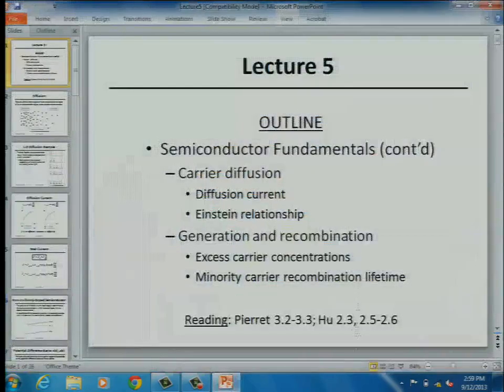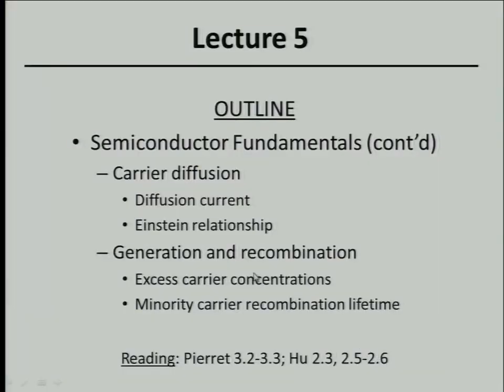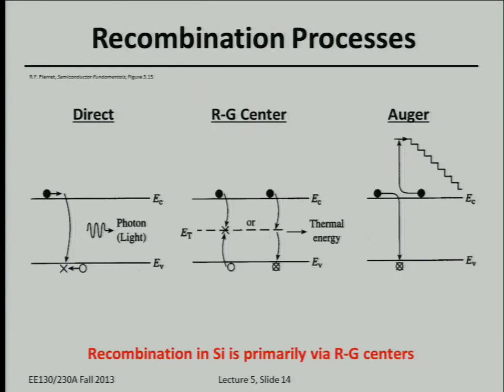Yeah, that's the case we talked about in the first column, right? That's band-to-band recombination that happens in gallium arsenide. So as you can see, in the first case, if the electrons just recombine with the holes directly, they could emit photons, by shining some light.